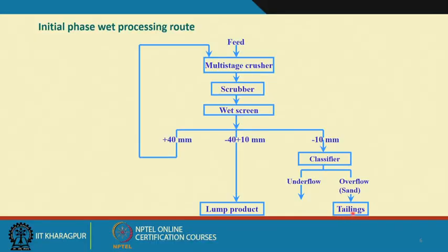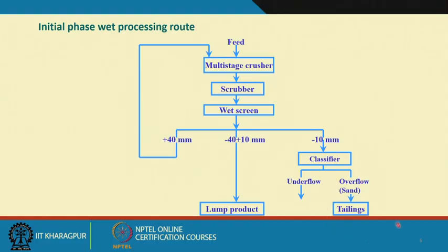But the trouble here is that you have higher percentages of alumina and silica. So you cannot directly use the tailings. Even if you make the pellets, you cannot directly charge them to blast furnaces, because they will have all the associated problems. So the beneficiation of these tailings, that is below 150 micrometer particles, has now become essential.